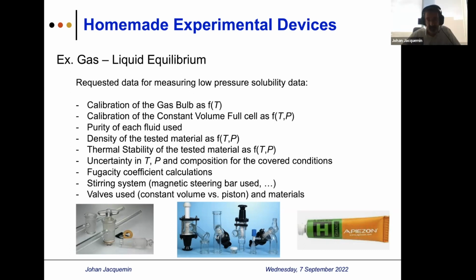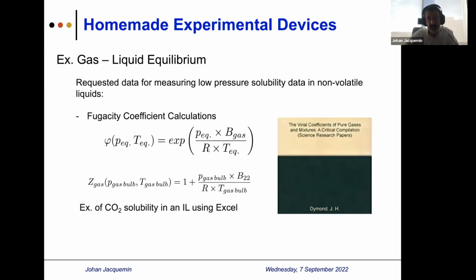And so on. And how can we cover the fugacity calculation as well? Do we have to include fugacity or not? That depends on the system, but if we want to be very strict, you must take into account fugacity calculation. In the case of data requests for non-volatile liquids like porous liquids, if we assume that porous liquids are non-volatile, and ionic liquids, fugacity calculation may be requested. I always include the fugacity correction, calculating the compressibility of the gas. And for that, I use a collection of Dymond and Smith data for different gases, and also for gas interaction, I would say water plus CO2, for example, cross virial coefficients and so on.